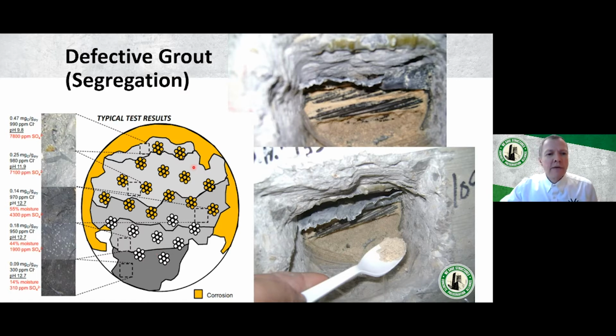In extreme cases, this soft material on the top may be so soft that it actually doesn't harden, and it's really more like wet clay, or if it dries out, as you see here in the pictures on the upper and lower right, it's more like chalky, very powdery material. So those are the two main things that typically lead to corrosion problems: voids and segregation or defective grout. And in the next portion of the presentation, I'd like to talk a little bit about techniques that can be used to identify areas where you have issues.